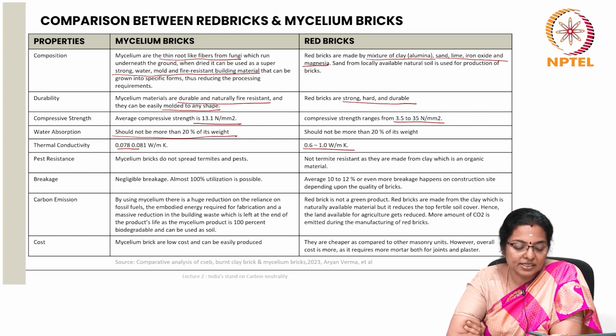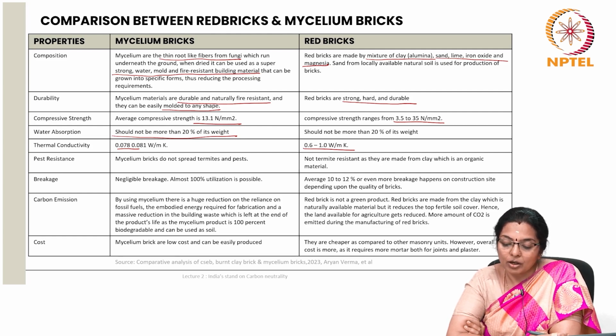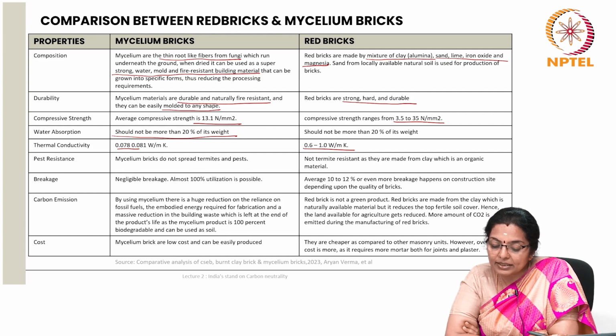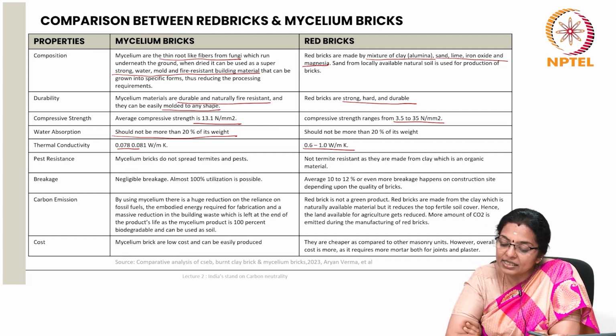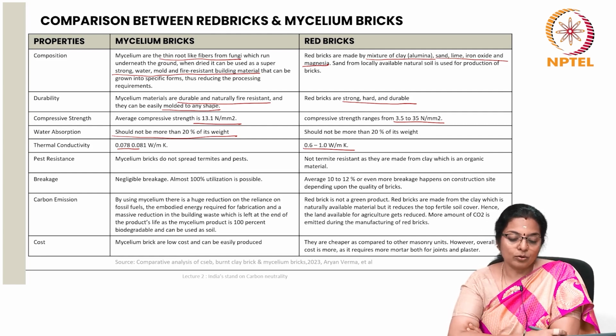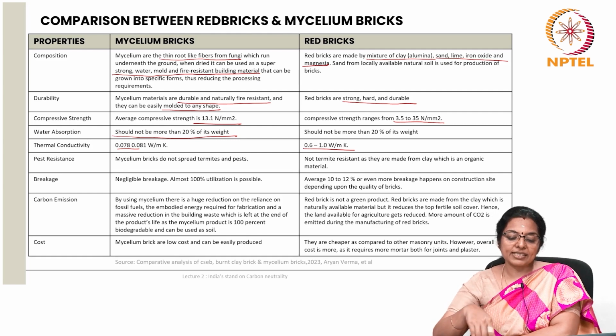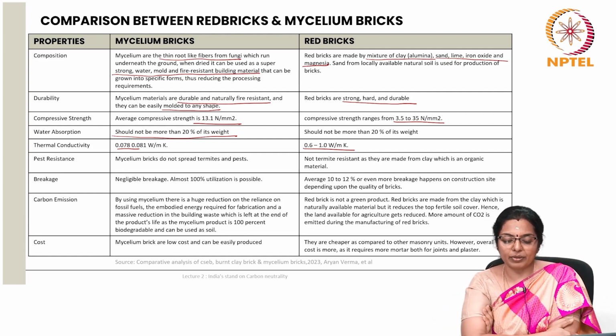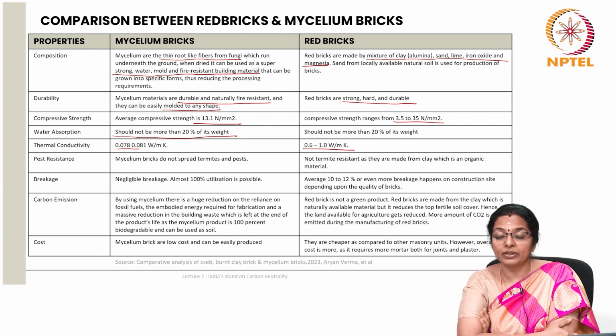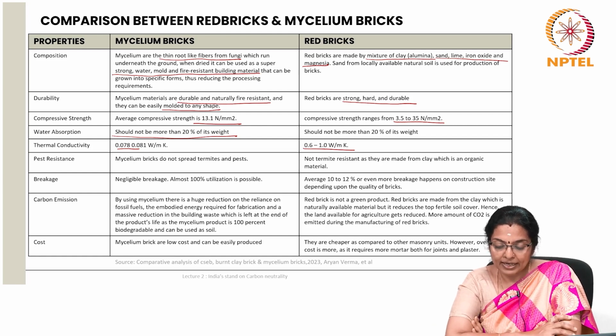Let's look at the pest resistance comparison. Mycelium bricks do not attract termites and pests. Now, red bricks are not termite resistant as they are made from clay, which is an organic material. Looking at the breakage properties, mycelium bricks have negligible breakage. Almost 100% of it can be utilized. Whereas on an average, 10 to 12% or even more breakage can happen on a construction site depending on the quality of bricks.